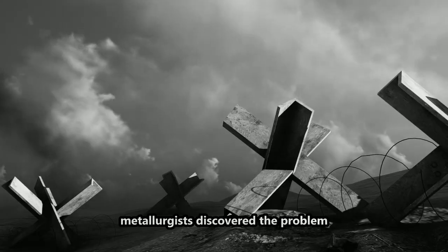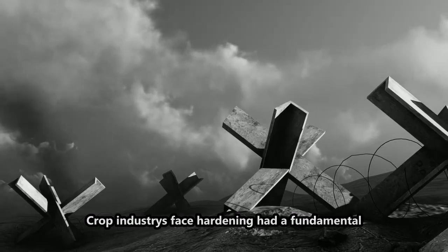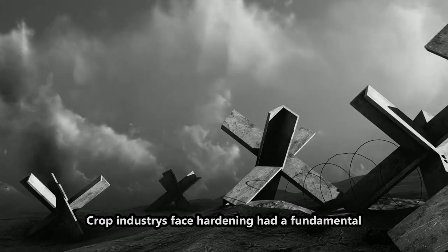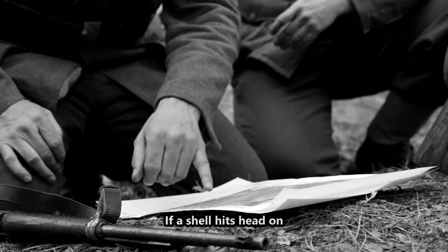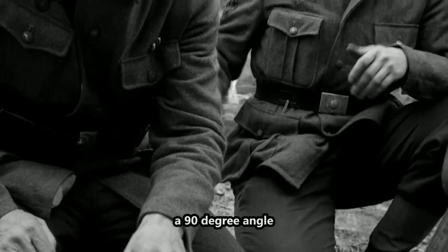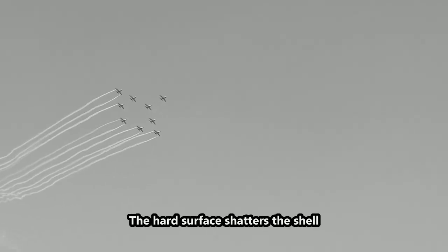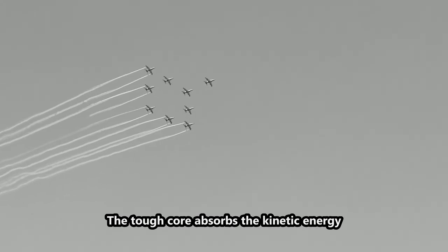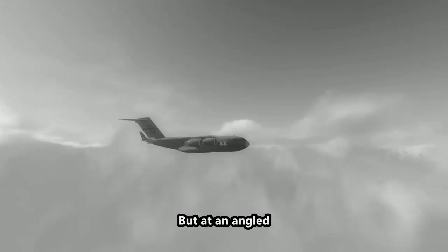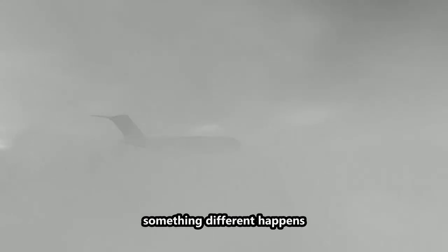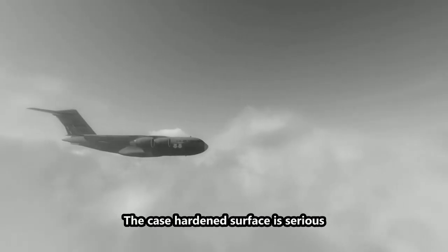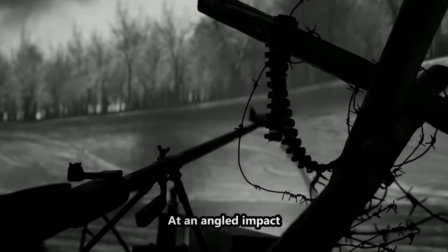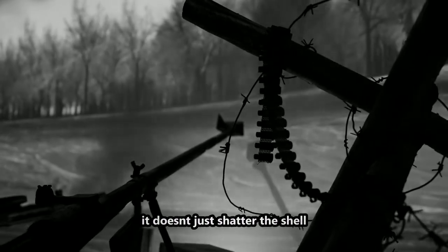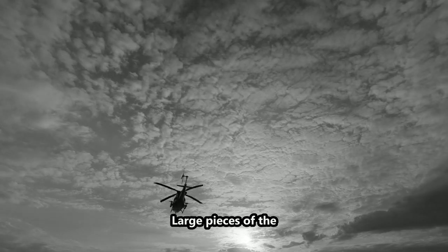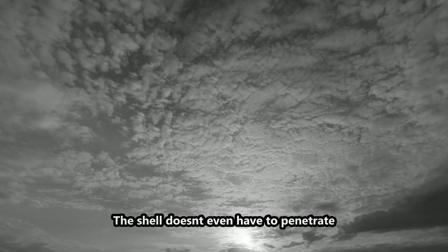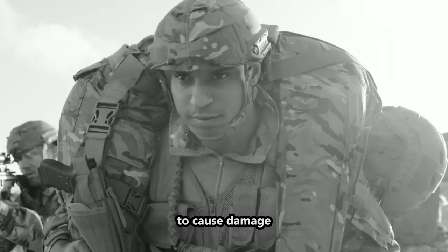But then, American metallurgists discovered the problem. Krupp Industries face hardening had a fundamental weakness: angled impacts. If a shell hits head-on, a 90-degree angle, face hardening works perfectly. The hard surface shatters the shell, the tough core absorbs the kinetic energy. But at an angled impact, 30 to 45 degrees, something different happens. The case-hardened surface is brittle. At an angled impact, it doesn't just shatter the shell, it shatters itself. Large pieces of the surface break off. Spalling. The shell doesn't even have to penetrate to cause damage.